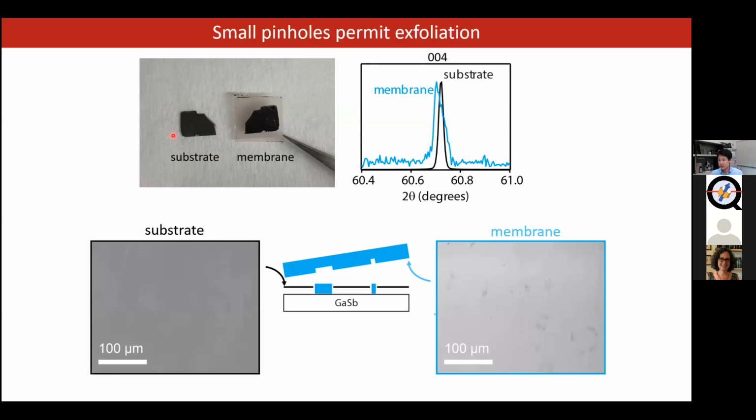Here's the sample. Here's the membrane that we've now exfoliated from that substrate. We can do X-ray diffraction to confirm that we've exfoliated a single crystalline membrane. And we can look at scanning electron microscopy of both the substrate side and the underside of the membrane after exfoliation. So there are pinholes, yes, but the pinholes are small enough that they don't impede long range the ability